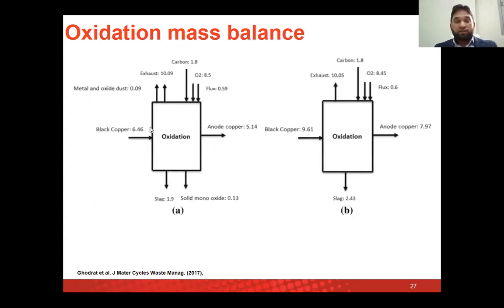So this is the oxidation stage. We put the black copper now in the oxidation furnace, and we give input carbon, we have oxygen, we have flux. We get some kind of oxides, metal and oxide dust, and then the output will be the anode grade copper, that is more than 99% pure copper.